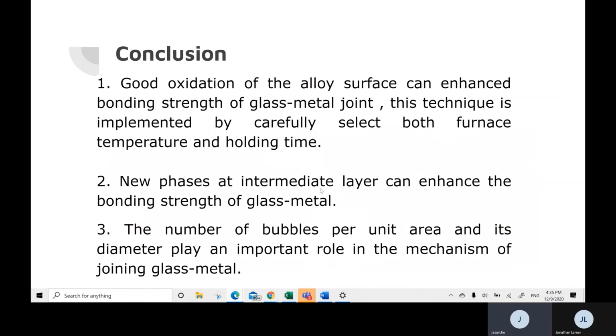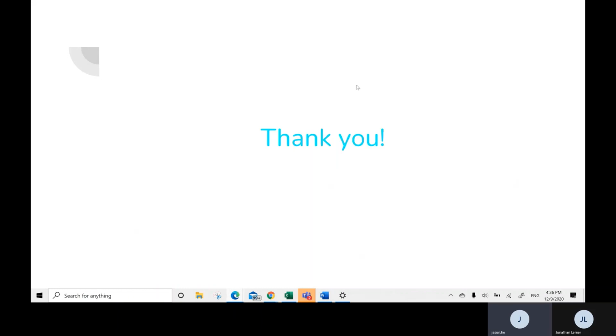The conclusion: 1. A good oxidation of the alloy surface can enhance bonding strength of glass metal joints. This technique is implemented by carefully selecting both furnace temperature and holding time. 2. New phases at intermediate layer can enhance the bonding strength of glass metal. 3. The number of bubbles per unit area and its diameter plays an important role in the mechanism of joining glass metal. Thank you very much.